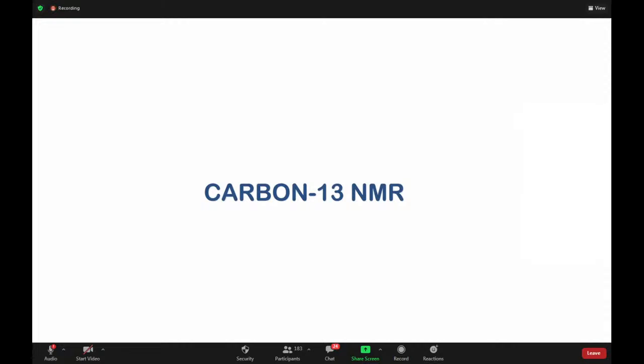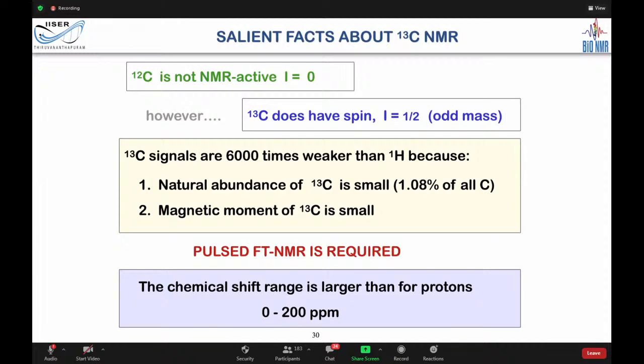Okay. So in carbon-13 NMR, you know that it is going to have very small abundance, because carbon-12 has even mass and even atomic number, so the spin is 0. But carbon-13 is spin half, and we should be able to observe it, but it's only 1.08%. And of course, the gyromagnetic ratio is 1/4 and the magnetic moment is 1/4, so the sensitivity is smaller.